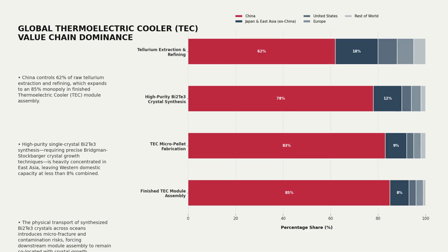China controls 62% of raw tellurium refining, which scales to an 85% monopoly in finished thermoelectric module assembly. Western domestic capacity across the entire value chain remains below 8%. This concentration is enforced by material science constraints. Synthesizing high-purity single-crystal bismuth telluride requires precise Bridgman-Stockbarger crystal growth techniques. Because these crystals are highly fragile, transoceanic transport introduces severe microfracture and contamination risks. Consequently, finished module assembly must remain co-located with East Asian crystal growth facilities.